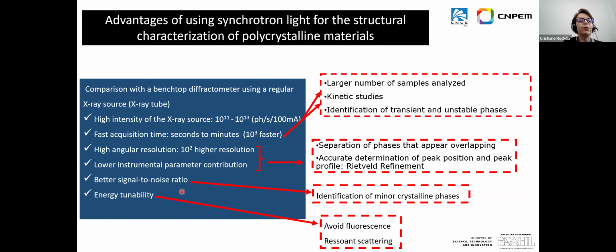At the synchrotron, we offer a much better signal-to-noise ratio, and with this, we can identify crystalline phases that are in minor quantity in your sample. And with the energy tunability, we can change the beamline energy and consequently the wavelength to avoid fluorescence and to have another methodology that's called resonance scattering.